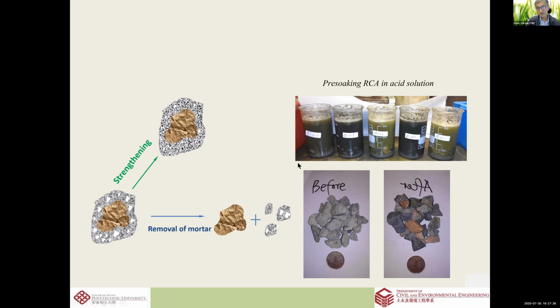We dissolved it in acid, hydrochloric acid. Before immersion it is coated with the paste or the mortar. After immersion, the paste has gone because it's dissolved in the acid, and you can see the exposed natural aggregate. This could be a treatment to retrieve the aggregate if we have a lack of aggregate, but this is very messy. We have a lot of waste, and it's very high cost.